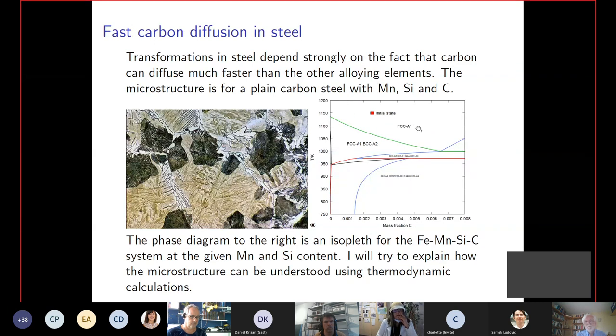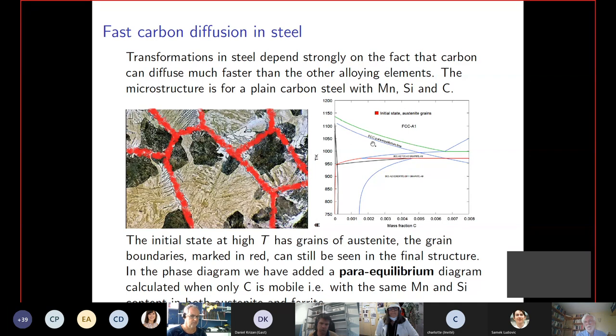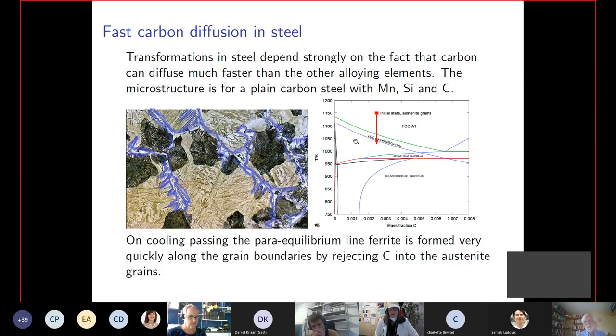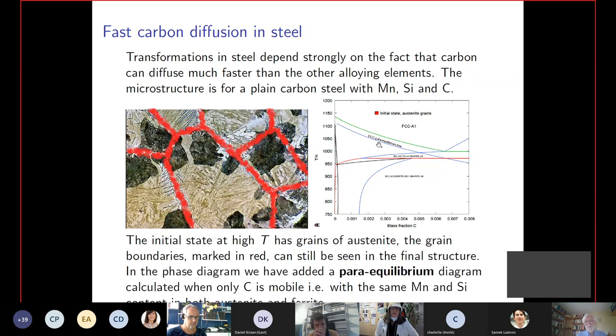This is an isopleth again, where you have an FCC region here. You have FCC, BCC, ferrite, carbide here, and you have graphite or cementite, which is stable at higher carbon content. So this is an equilibrium phase diagram. You can also calculate what is known as a para-equilibrium phase diagram. In this para-equilibrium, you assume that carbon is the only element which can diffuse. You assume that manganese and silicon remain fixed, as if they were not moving in the system. So you can calculate the equilibrium if only carbon diffuses, because carbon is an interstitial element and it can diffuse very quickly.